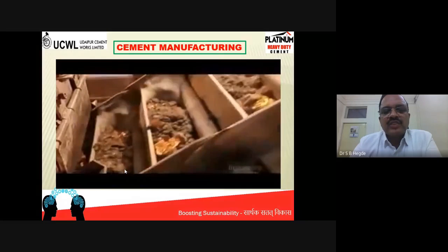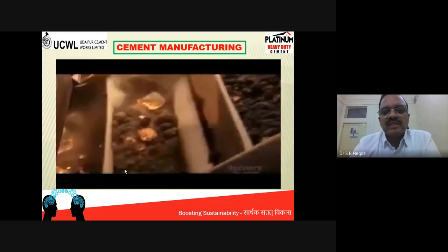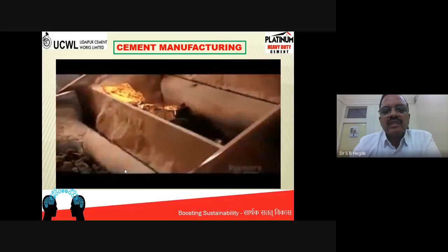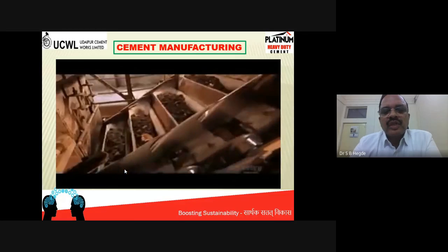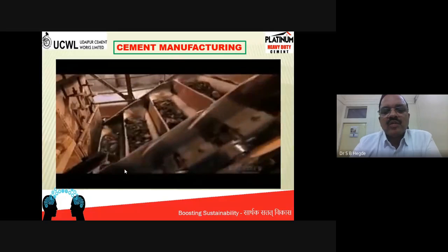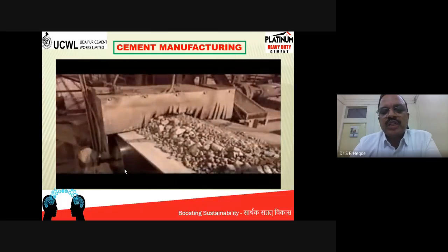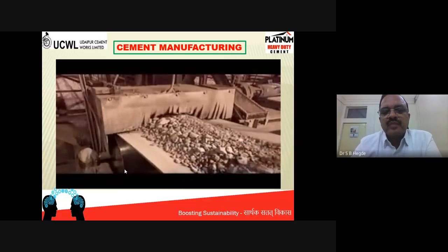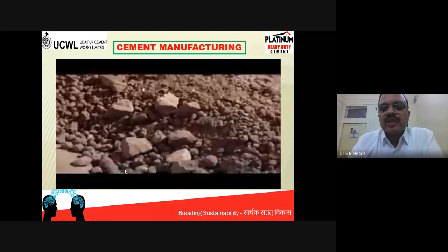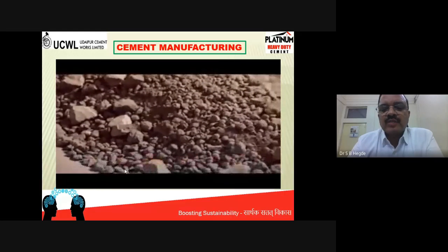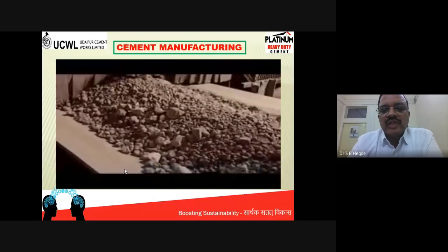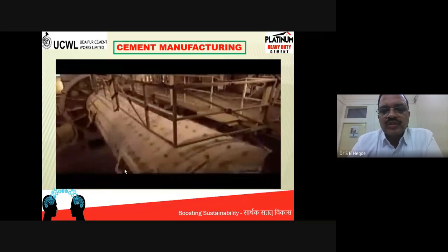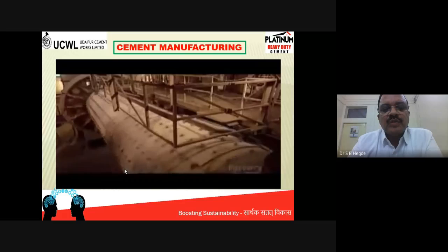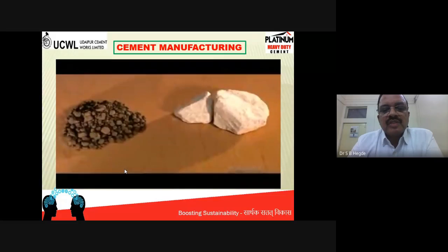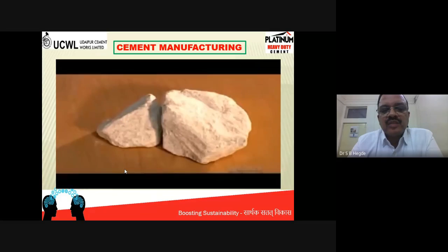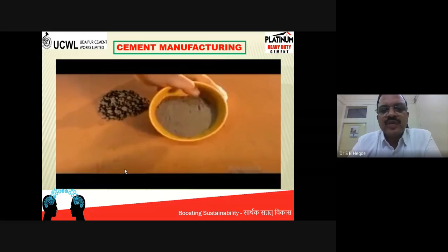That cooled material is called clinker, and it is transported into a clinker silo where it is stored, and then taken out from the silo and put into a cement mill. You can see the belt containing clinker and gypsum materials going inside the cement mill, where it will be ground and cement will be produced. This is the cement mill. This is the gypsum they add to produce OPC cement.